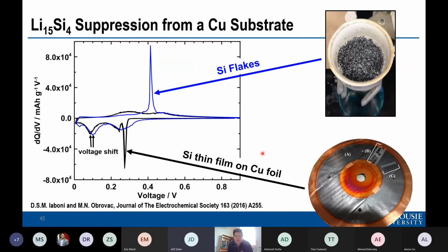And we decided to measure that as student Douglas Iaboni. This was his master's project, because we realized, well, this 15-4 phase, you form it when the potential goes below 50 millivolts. But on a thin film, you can shift the potential by more than 100 millivolts negative. That means you're shifting that 15-4 formation below 0 volts. So theoretically, you should never see it on a thin film.